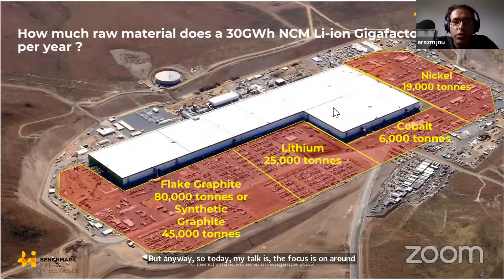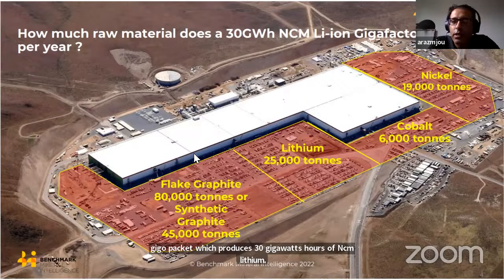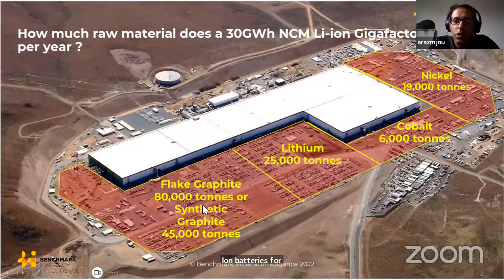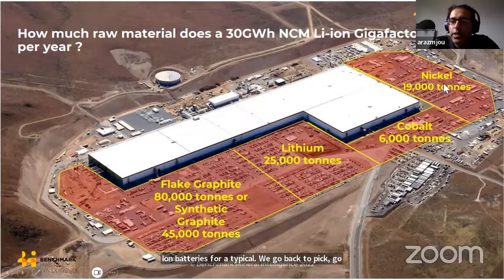As you can see here, this is a typical gigafactory which produces 30 gigawatt hours of NCM lithium-ion batteries. For a typical gigafactory, we need somewhere around 19,000 tons of nickel, 6,000 tons of cobalt, 25,000 tons of lithium per annum, and around 80,000 tons of synthetic graphite or flake graphite per annum.